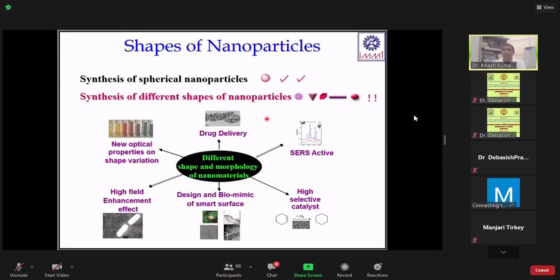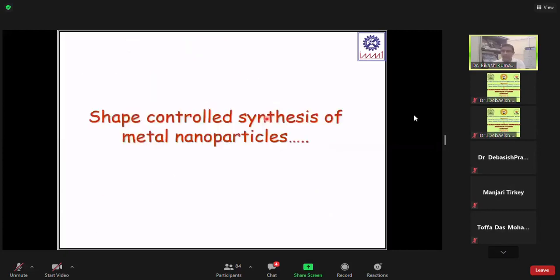So there is a lot of tendency, and a lot of effort has been carried out on how to control the growth of nanoparticles during the synthesis, so that you can go to one directional growth of nanoparticles, making a rod shape nanoparticle or another shape by tuning that. We have observed that this green synthesis method is quite vital. By this method, you can get very different kinds of shapes of nanoparticles, because these plant extracts and biomolecules have very beautiful structure and capacity, so that they can interact with the atoms generated from the metal precursors to give rise to a very nice shape.